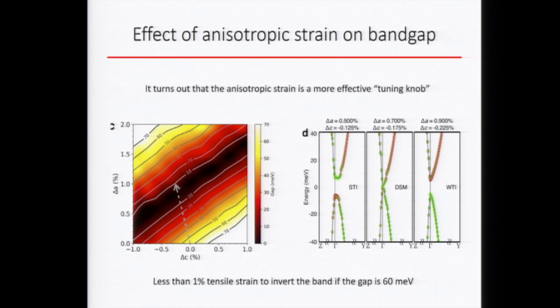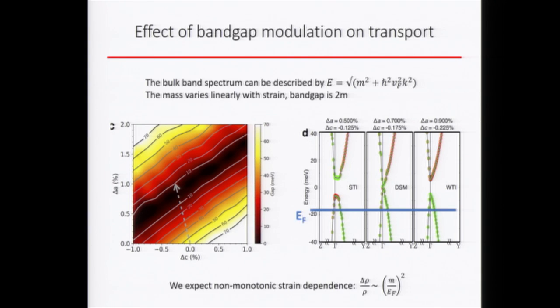So let's talk about what we expect to see in transport when you're going across this topological phase transition. In reality, you always have some finite carrier, so your Fermi level is not in the gap or at the Dirac point. If you're really in the gap, then you probably will see some insulator to semi-metal to insulator transition, plus some effect of surface state. But in reality, with this small gap semiconductor, you always have some ionized impurity, and therefore some residual carrier density. Our estimate of the Fermi level is somewhere around here, like 10 millivolts or less.